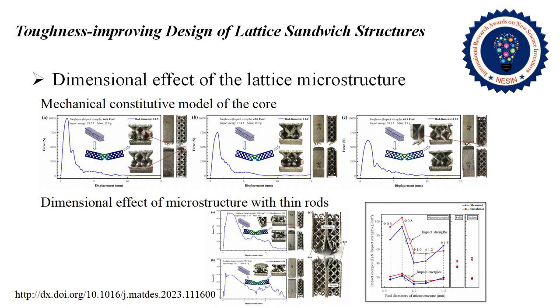However, when the top skin is loaded, it produces several plastic hinges, which enhance the energy absorption efficiency. In addition, the expansion of the plastic zone is also conducive to the unloading of stress at the crack tip, and increasing the fracture resistance of the top skin. The deformed skin extrudes the internal space of the structure, resulting in deformation and damage to the core. Then, the impact toughness of the samples is further improved.